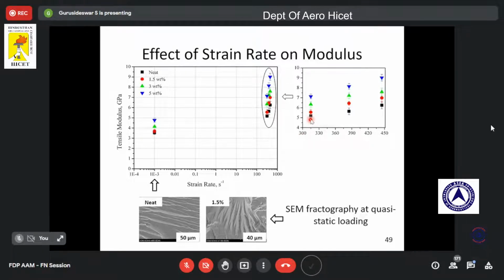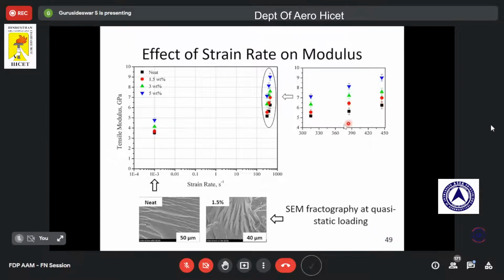You see the black one. And similarly, when the strain rate increases from 315 to 385, there is an increase to around 5.5. Now, a further increase in the strain rate leads to again an increase in the modulus, to around 6 gigapascal. So this is what we observe from this graph. This trend has been followed for other samples also.